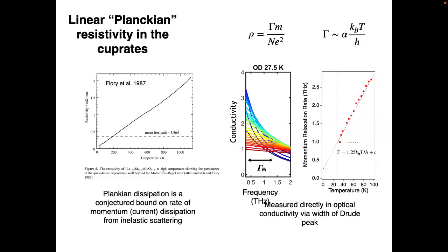What we're interested in here is resistivity as a function of temperature in lanthanum strontium copper oxide. That's the superconducting transition way down there, 30 or 40 Kelvin. The remarkable thing about this data is that it's linear in temperature all the way up to the melting temperature of lanthanum strontium copper oxide, well over 1,000 degrees Kelvin. One of the other remarkable things is that it's linear and it just smoothly passes through various different scales in the problem without any regard to them.